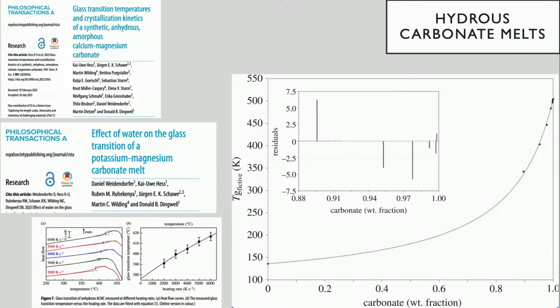And with that, we're able to step into an area which is more physical chemistry than geology, which is, here you have the carbonate melt weight fraction. This is pure carbonate, and over here is pure water. And some of you may know that actually all liquids have a glass transition. Water also has a glass transition, and water glass transition is at about 130, 140 degrees Kelvin. And here you can see the effect of water on the glass transition of a carbonate liquid as this curve falls with the addition of water. And you can see something very interesting, which is that you can continuously extrapolate that to the glass transition of water. So the system water carbonate gives you a continuous variation of glass transition. Why would I be excited about that? Because silicates, normal, volcanic, rock-forming systems, they do not show this. They show a huge cliff between the property values of water and that of hydrous silicate liquids.